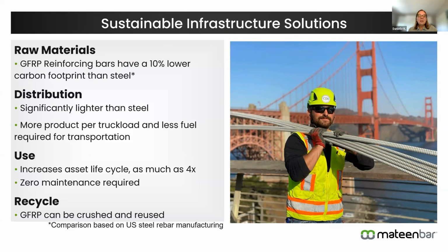I said I would talk about sustainability a bit here. So there are environmental product declarations, if that's something that you all are requiring for GFRP. In full transparency, Mateen Bar is working on ours now, but there are published EPDs for GFRP materials. And if we look at those EPDs and we consider a comparison to steel, comparing to the industry average EPD that's published by CRSI, we see about a 10% decrease just in terms of the raw material. Again, if we translate that to fewer trucks, more product per truckload, we're saving in that distribution phase.